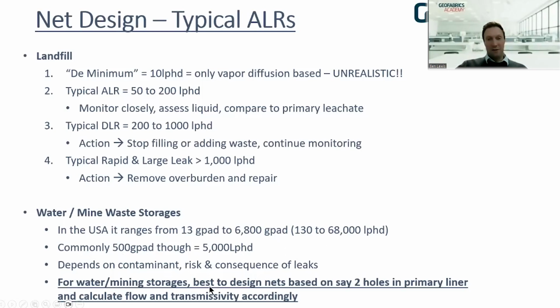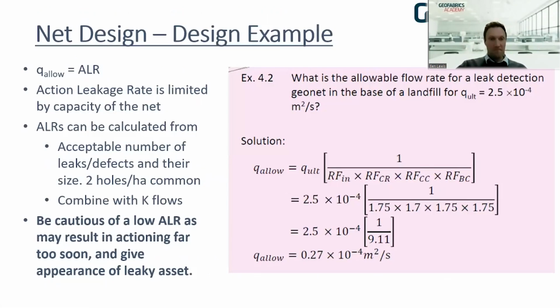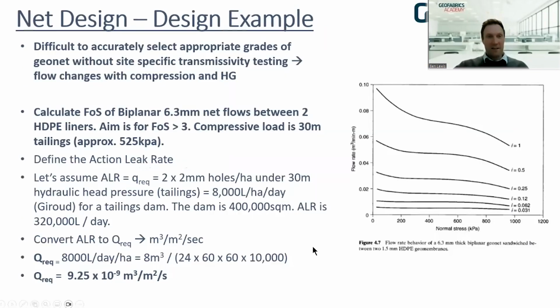But that really comes down to what your head pressures are. I think the example here considers, say, 2 holes per hectare is acceptable. And then based on that, you can work out what the leakage rate might be. Now, the example here I've got is, it's quite difficult to accurately select grades of geonets without specific transmissivity testing. Not all suppliers have a huge amount of transmissivity testing. There's always one value on a data sheet, but that is only specific to the compressive load and the hydraulic conductivity, hydraulic gradient, sorry.